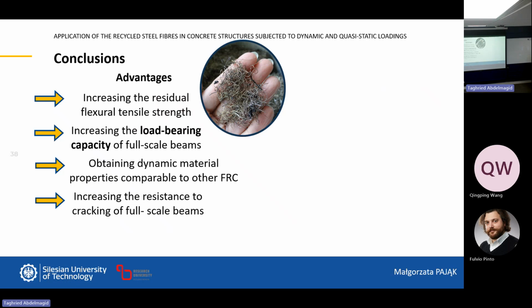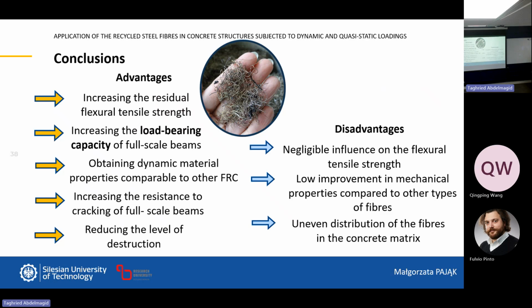Of course, I must say here, this increase in flexural tensile strength, there are the residual strengths. So for the crack mouth opening 0.5, 1.5, and so on. So this is also the parameter that is included in calculation of the serviceability limit state. So it's the same. However, we didn't achieve the decrease in the distance between the cracks. And of course, reduction of the level of destruction in every condition. So quasi-static, dynamics, it always reduces the level of destruction.